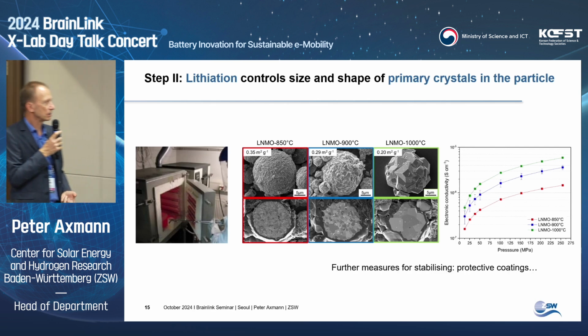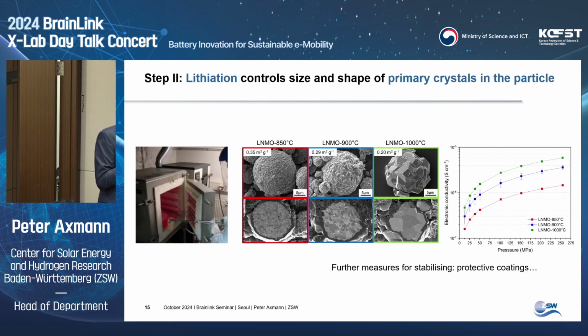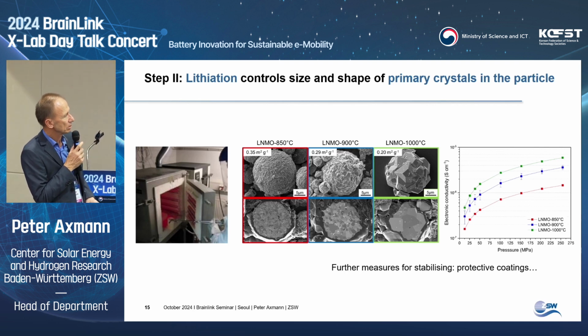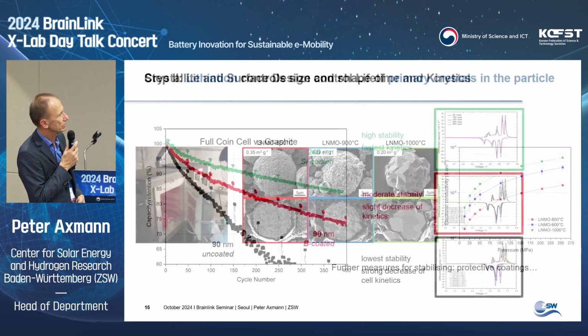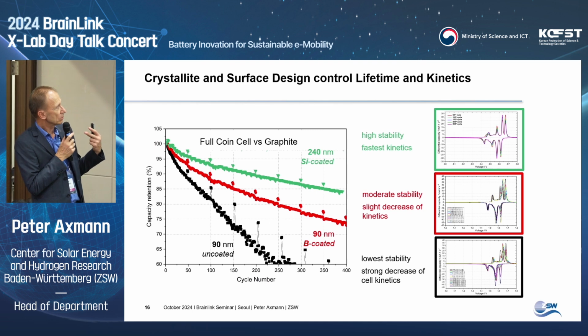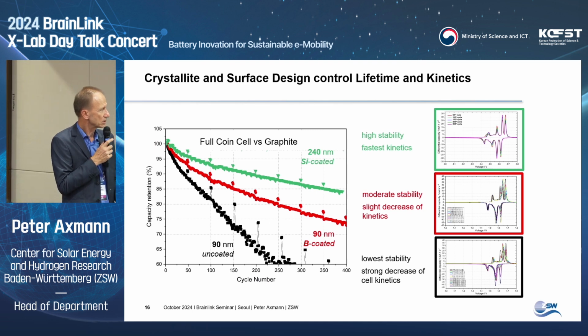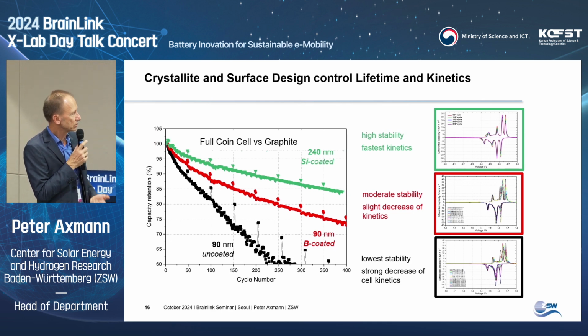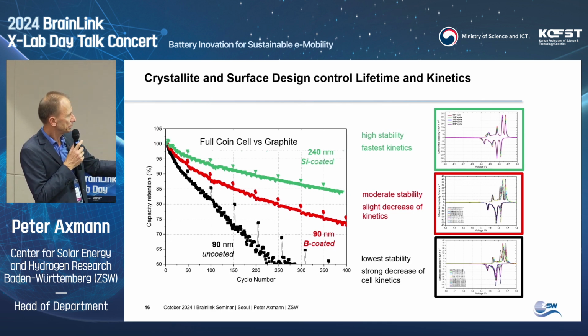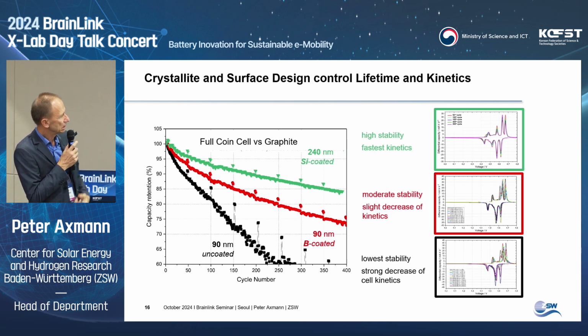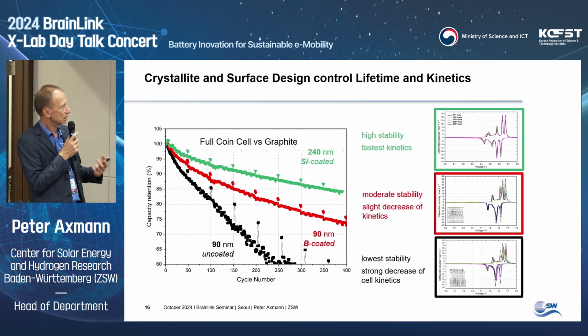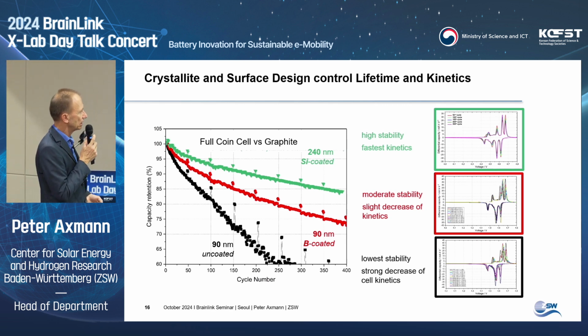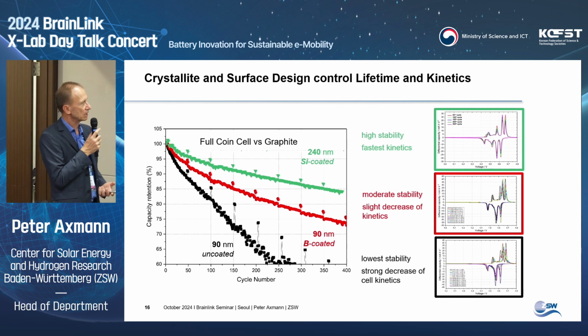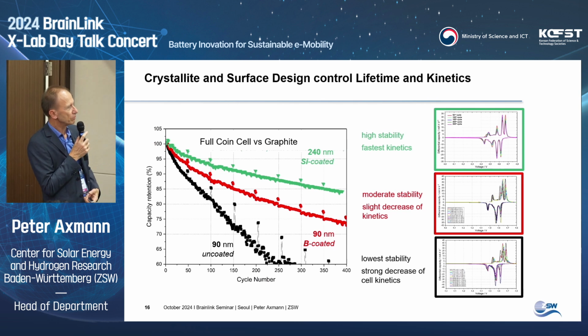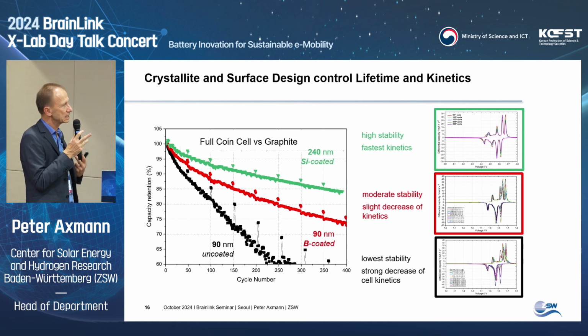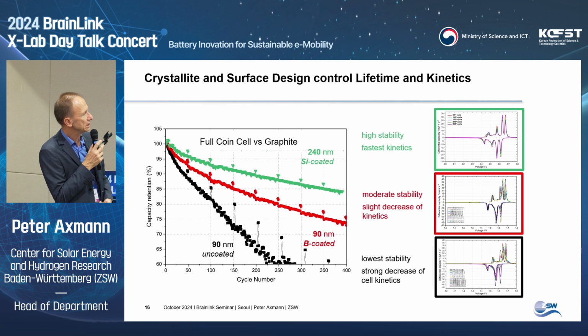On the other hand, you can take further measures for stabilizing. You can go to protective coatings. And I just would like to compare the effect of crystallite size and protective coatings here. So what you see here is a coin full cell setup against graphite in a standard, not stabilized electrolyte. What is shown here for a normal material which is uncoated, the black line, a 90 nanometer primary crystallite size material, we can reach about 100 cycles until we reach the end of life criterion at 80% of the initial charge. If we then coat this material with 0.5% boron oxides, same material, we can extend, here the red curve, the capacity and the stability by a factor of 2.5.